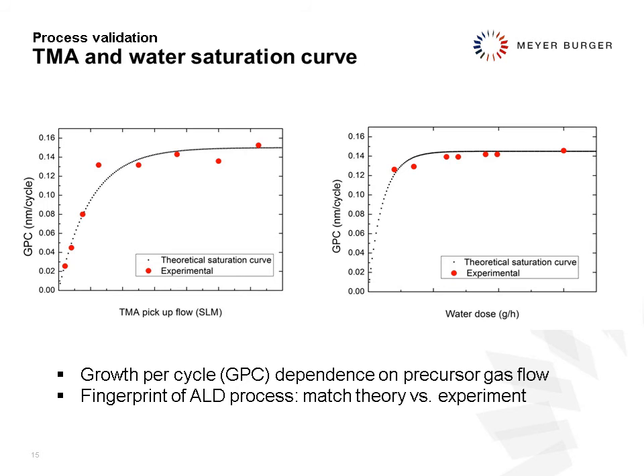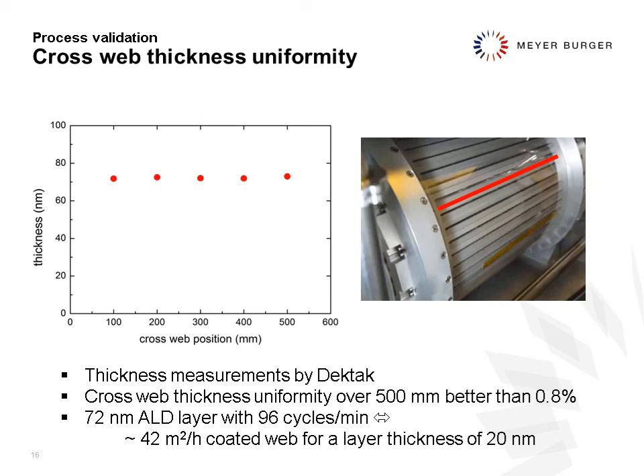Now, this growth per cycle is actually a signature of the machine. We can therefore verify if the machine works properly, if we achieve a certain theoretical saturation curve. And we can influence this by changing the TMA pickup flow or the water dose. And what we see is that we could match in our machine this theoretical level, which means we have an ALD process in place. So we went from a very classical time-based ALD, we moved it to spatial, and we find it again. So all good. Now, let's see what the advantages are of having something like that.